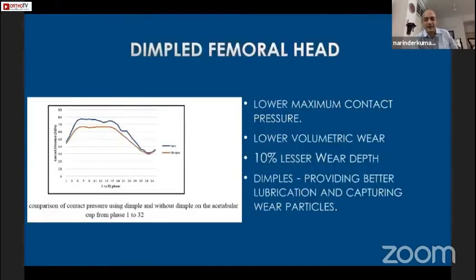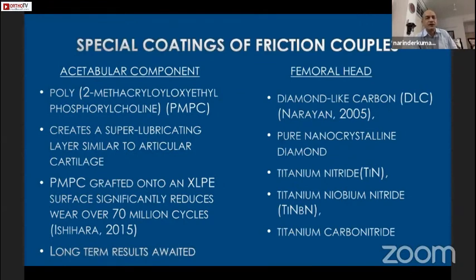How? The dimpled femoral head, just like surface textured poly, had lesser maximum contact pressure, lower volumetric wear, and 10% lesser wear depth has been documented. The dimples provide better lubrication and allow capturing of the wear particles out of the fluid film, leading to lesser third body wear even. The special coatings which are being explored both on the acetabular side and the femoral head, none of them is commercially launched, but they are there, which are expected to change the lubrication to fluid film lubrication. I hope they work out. Long-term results are not as yet available. Probably it's only animal studies which are going on.